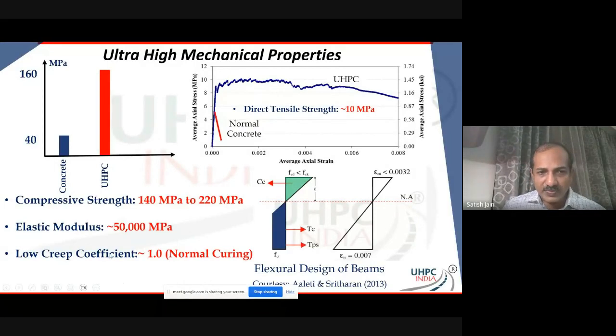Elastic modulus, generally very, very high, 50 gigapascals or 50,000 megapascals. Third thing, low creep coefficient, about one with normal curing, right? So concrete has a creep coefficient of 2, whereas UHPC, you can get about 1.